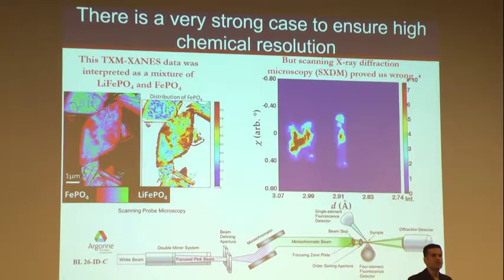You need a lot of energy resolution to be able to tell if you have iron 2 and iron 3 in the same structure or in different structures. In the TXM experiment, you're limited by how much beam time you get. And so you would get 15, 20 energy points. It's not enough to get the energy resolution that you would need to discern the 2 phases. Diffraction doesn't have that problem. You're really very sensitive because you have a large 2 theta separation between the states. Not only is there an intermediate, but there's miscibility between the fully lithiated state and the partially lithiated state.